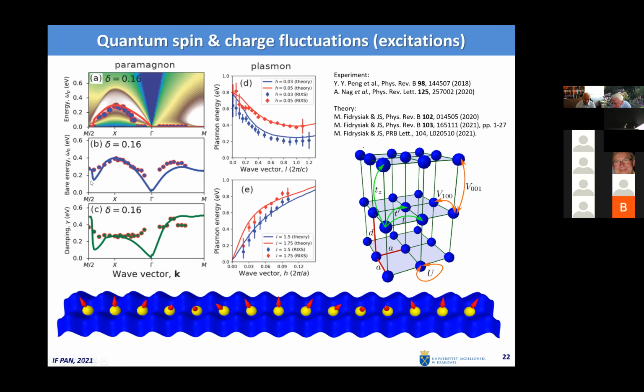Here is, as you can see, the bare energy of the magnons. Here is the effective energy, the so-called, well, I won't define what I mean by effective, by bare, but unfortunately the damping rate is not so well reproduced. And as you can see, near the gamma point, experiment shows nothing. In our case, we show the maximum, there is somewhat of a discrepancy here in the half-width. Whereas for plasmons in three dimensions, they are very well recovered.